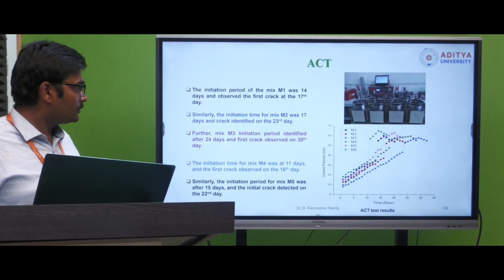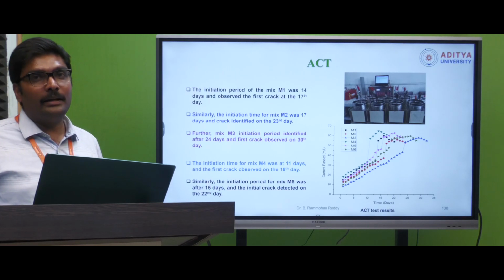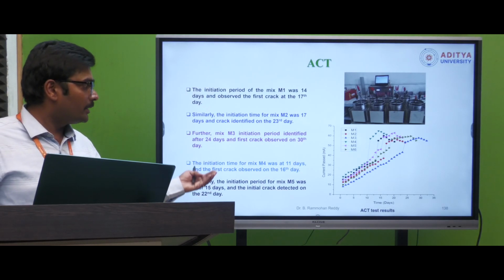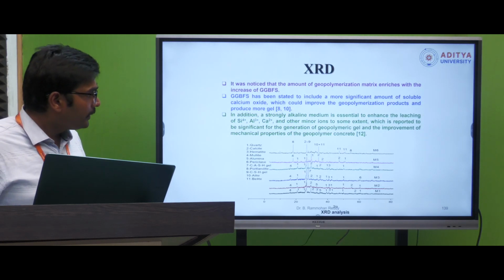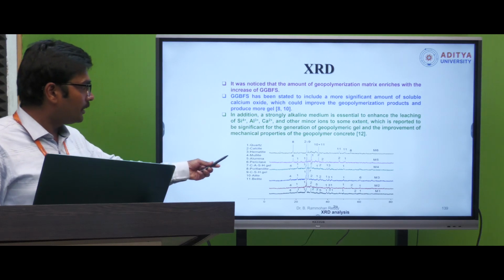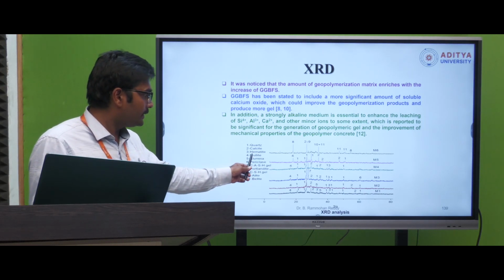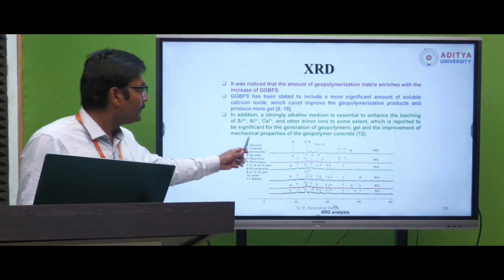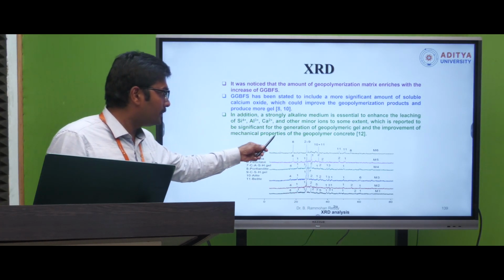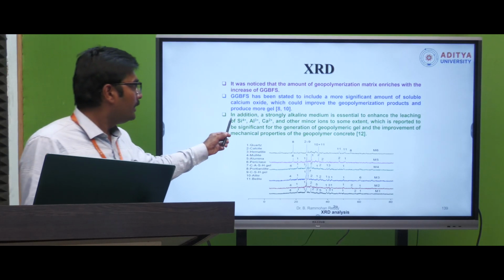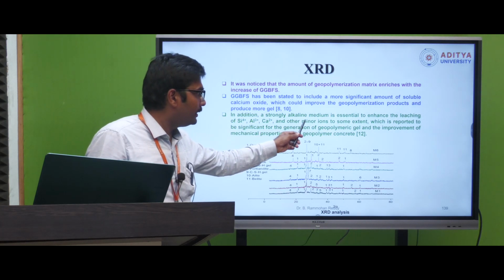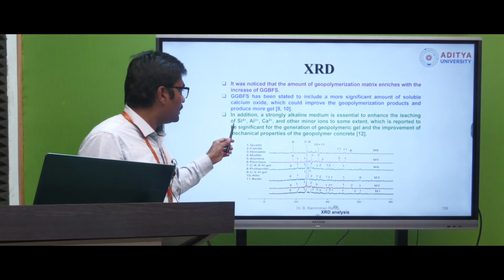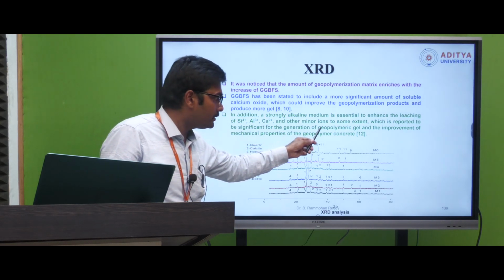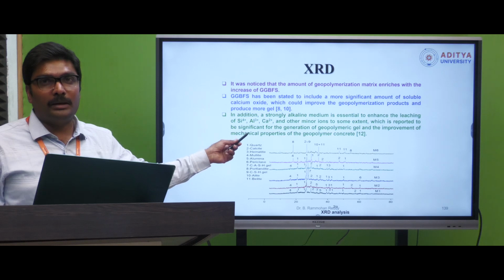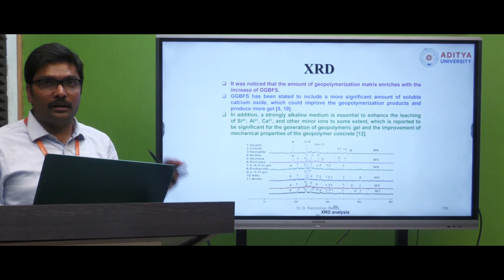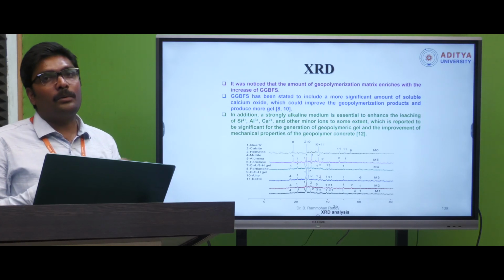And we have done the accelerated corrosion test, and it also indicates that increasing the GGBS content in the geopolymer concrete produced better results. Through XRD we analyzed the formation of various phases here: quartz, calcite, hematite, and all the things which were indicated here. You can see this point is an important point and indicates how the strength is developing. In addition, a strongly alkaline medium is essential to enhance the leaching of silica, alumina, calcium and other ions. This leaching plays a major role in strength attainment, but the leaching of these ions must be within the limit. If it crosses the limit, the strength improvement will be reduced.